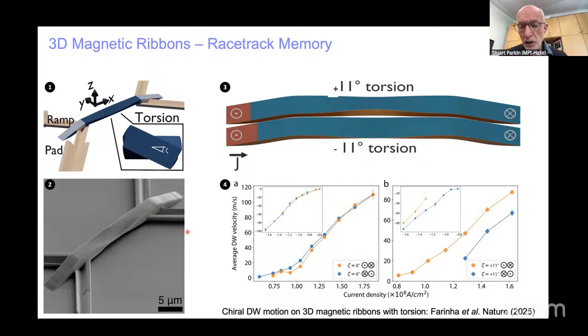And what we demonstrated was that the motion of the chiral domain walls is influenced by the chiral surface on which they are deposited, and that whether the chirality of this surface has a torsion to the left or to the right strongly influences the motion of the domain walls. So this is the first demonstration of the interaction of a geometrical and a spin chirality.